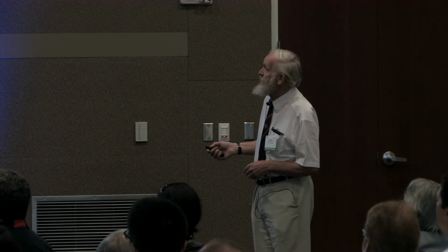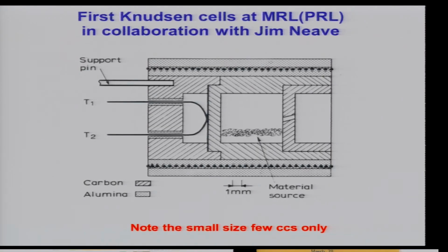The cells were homemade, as Al said. Just look at the dimension here, 1 millimeter. These were not exactly large cells. They were nevertheless true Knudsen cells. You can see that the internal surface area here is very large compared with the size of the aperture. That's a second requirement for a Knudsen cell. And what we paid attention to was making sure we measured the temperature accurately. So there's the thermocouple welded to a plate here, so it really does measure accurately the source temperature.